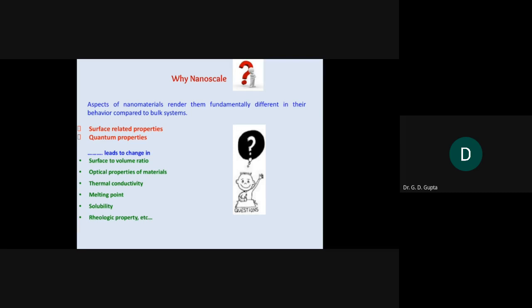Even the rheologic property also gets changed. So with the same gold particles, we know that gold appears yellow, but when we reduce the size of the gold particles below 50 nanometers, it appears red. And when it comes below 10 nanometers, the same gold appears black. So by reducing the size of the particles into the nano range, the properties get changed.